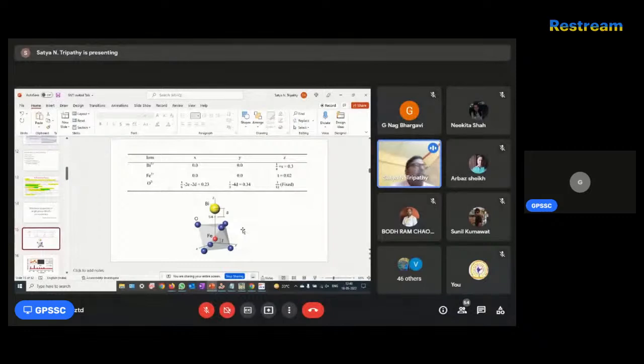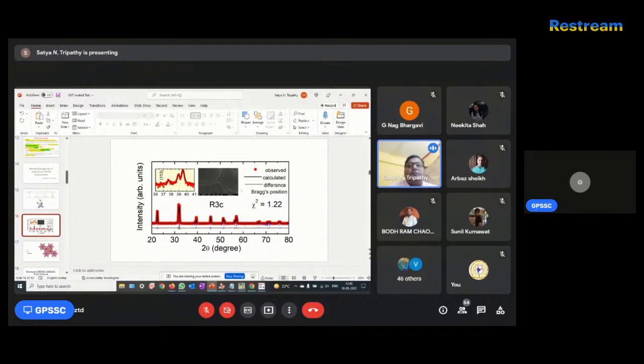So I have collected my data. This is the Rietveld refinement of the bismuth ferrite sample, with intensity on the y-axis and 2 theta on the x-axis. Here dots are observed, black is calculated, the gray line below is the difference, and the Bragg positions are presented. One of the characteristic reflections is 113, which arises because bismuth ferrite is ABO3, so it has BO6 octahedra. Due to that rotation this plane appears, and because these are oxygen planes, it has less intensity. This is our figure.